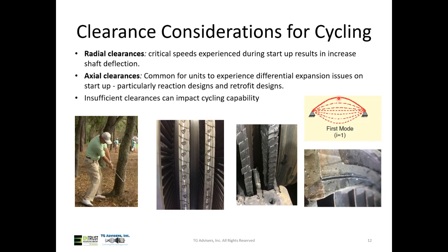We're going to have differential expansion because everything's going to heat up differently. Rotor casing, rotor length is also impacted by heat, but it's also impacted by speed. So a lot of stuff going on. We don't want things to touch that aren't supposed to. Metal on metal can create quite a bit of damage. So making sure we have sufficient clearances is important for cycling.